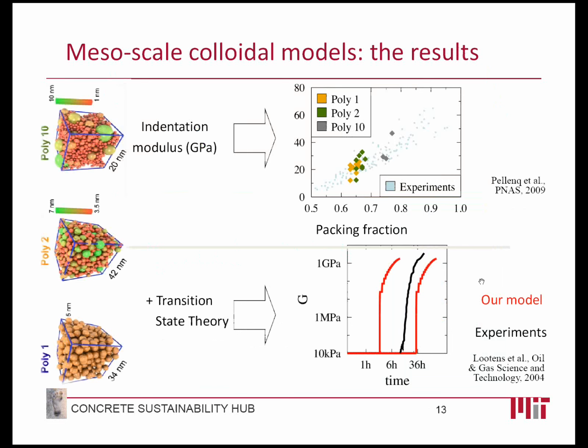So next is the illustration of this. We have an assembly of grains in those boxes with some polydispersity in terms of grain size. For instance, what's called poly10 is where you have a large distribution of possible sizes of CSH grain. That model allows us to predict the mechanical properties, which is the first top plot: the elastic property of cement as a function of the packing fraction. The green, yellow and gray data points are our simulations, and the small blue dots are the experiment, as measured in the lab by experimentalists using nano indentation.